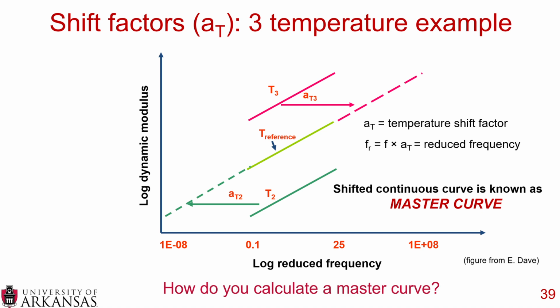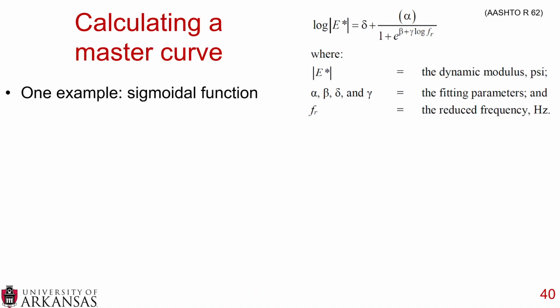Now, how do you calculate this master curve? Well, one example is a sigmoidal function. So this is in AASHTO R62, but you can see that you have a dynamic modulus, the log of the dynamic modulus, and that equals various fitting parameters and the reduced frequency. This is just one example. This is in the standard, so this is kind of the default go-to. There are other ways to do it as well.